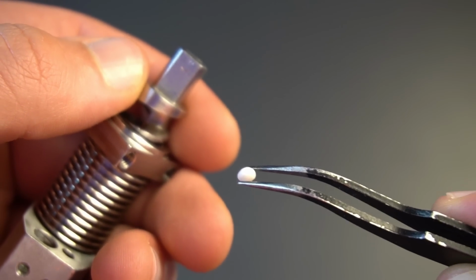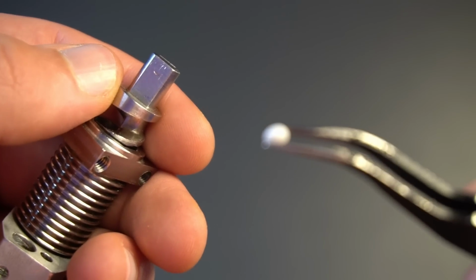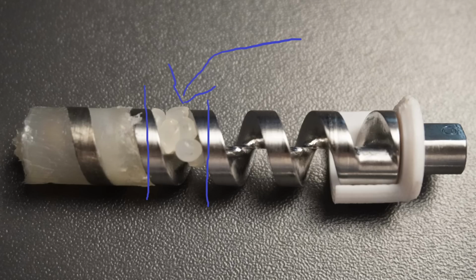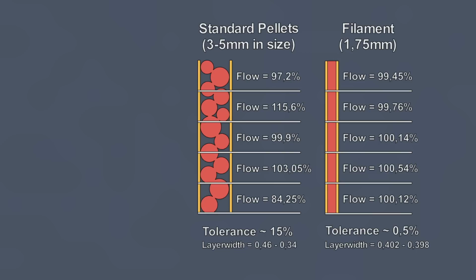And when you try to fit them inside the extruder barrel I showed you earlier, they will stack up very unevenly, which in the end results in an uneven flow rate that fluctuates around 15%. 15% sounds very dramatic, but in reality the difference is hardly visible. Only when you get very close, and I'm gonna show you now what I mean by that.